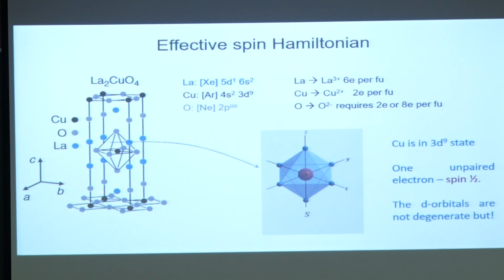So, what is important for us is to see that these copper ions, which are depicted here with the black balls, actually form a square lattice. You can see that square lattice over here, and between any two copper ions there is an oxygen, okay, and this copper oxygen octahedra which you see over here is slightly stretched along the z axis, okay.